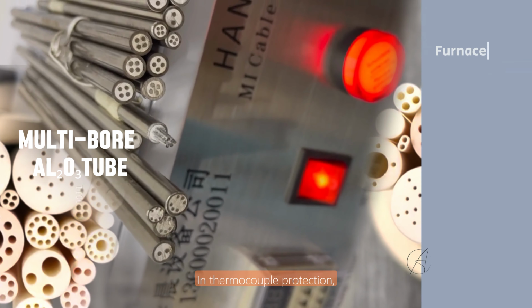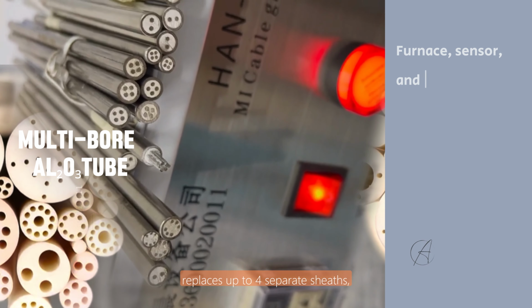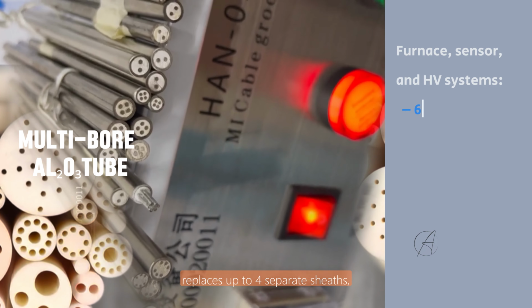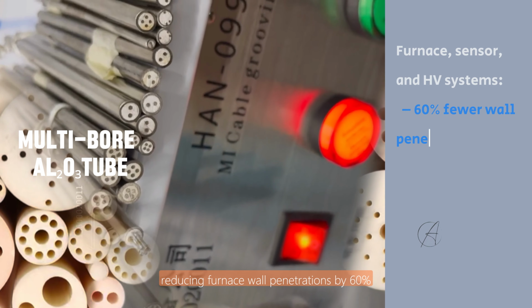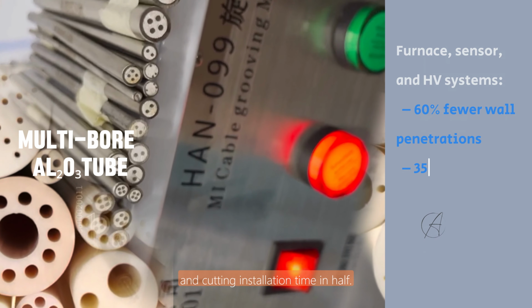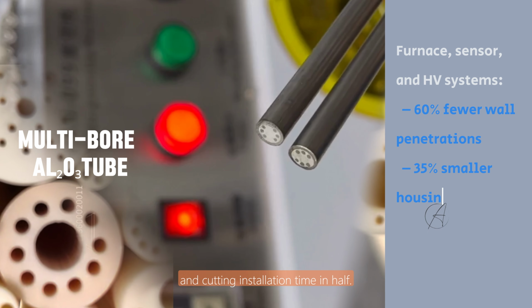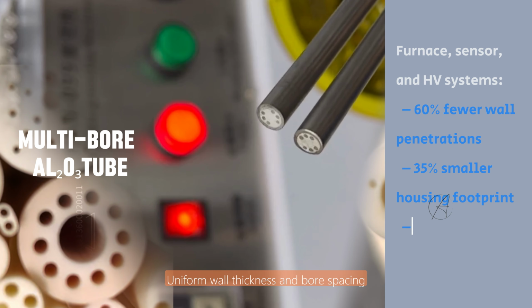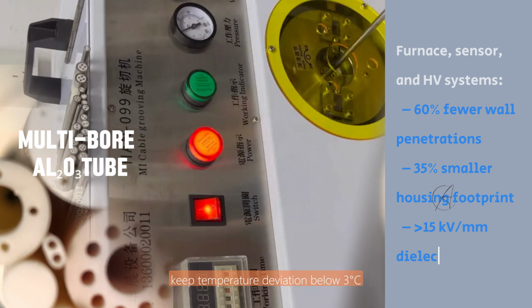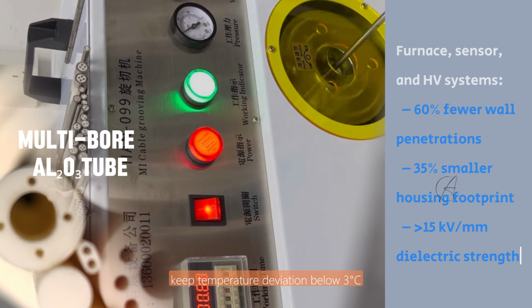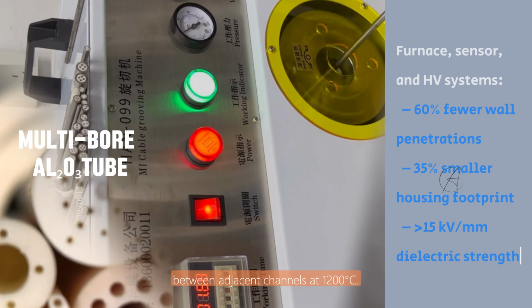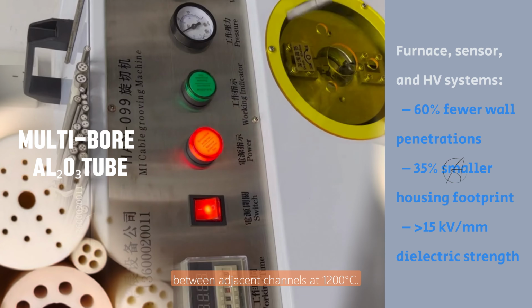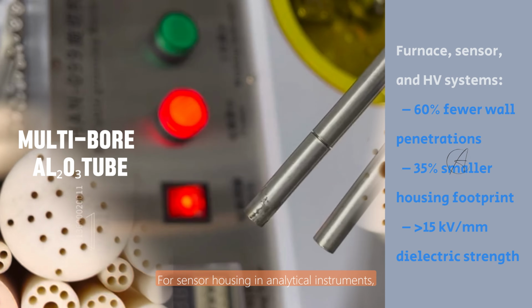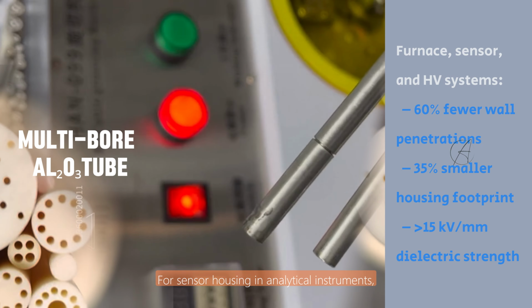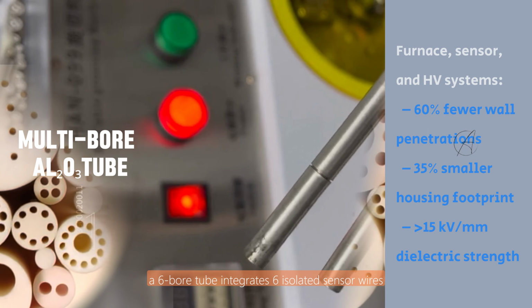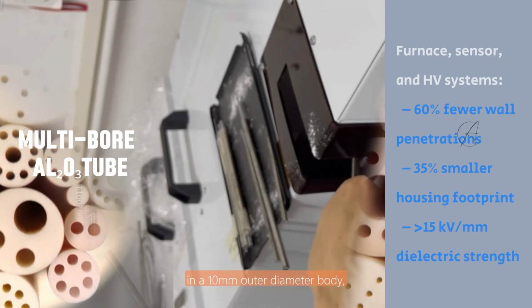In thermocouple protection, a single 4-bore tube replaces up to 4 separate sheaths, reducing furnace wall penetrations by 60% and cutting installation time in half. Uniform wall thickness and bore spacing keep temperature deviation below 3 degrees Celsius between adjacent channels at 1,000 to 1,100 degrees Celsius. For sensor housing and analytical instruments, a 6-bore tube integrates 6 isolated sensor wires in a 10 mm